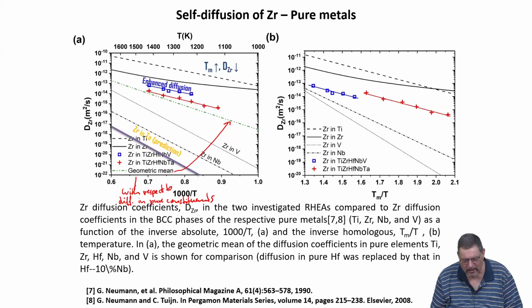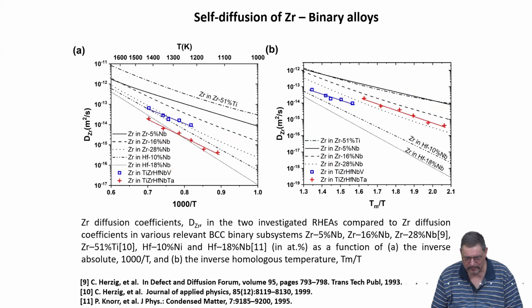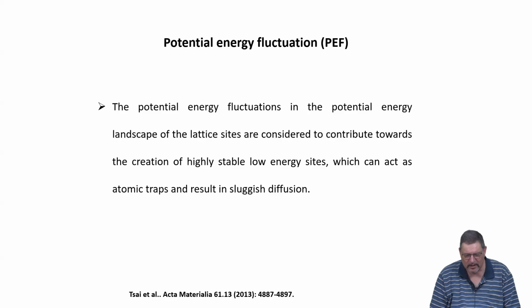Yeah, so a little bit enhanced diffusion, but I wouldn't say it is much. And here it's just again compared zirconium diffusion coefficients in the two refractory high entropy alloys to various other BCC matrices. And then again for the absolute temperature and for the homologous temperature. And again, not much of a difference.